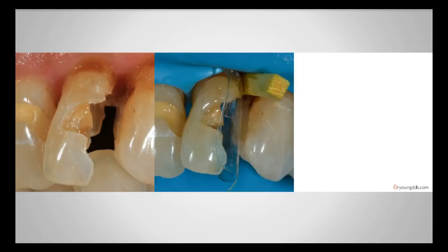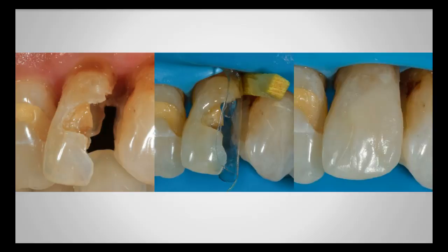And then I'll use heated composite too, and I'll use it in a two-stage injection mold essentially, and I'm going to inject APX first for my dentin back layer, and then I'm going to come in and inject right on top of it with an enamel layer and bulk cure from both sides and a lower stress C factor on this type of restoration. I'm going to basically get that restoration. And I know that that's going to last for many, many years because we've not stressed the bond, we've done things correctly.